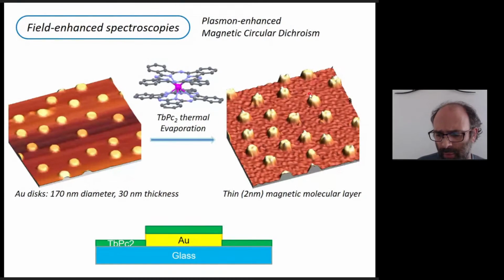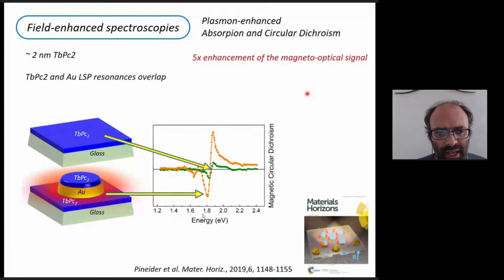This is a paper we published a few years ago in which we placed a thin film of magnetic molecules, terbium bisphthalocyanine. This is a single molecule magnet. We placed it on top of plasmonic nanoantennas made of gold on a glass substrate, and we could see that there is a rather strong enhancement of the magneto-optical response of these molecules when we have the plasmon resonance overlapping the optical absorption of the molecule. Okay, so this is an interesting thing.